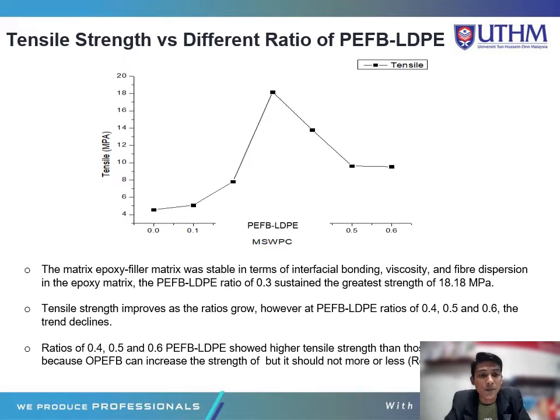The epoxy matrix of the filler matrix was stable in terms of interfacial bonding, viscosity, and fiber dispersion in the epoxy matrix. PEFB ratio 0.3 sustained the greatest strength of 18.18 MPa. The tensile strength improved as the ratio grew. However, at PEFB ratios 0.4, 0.5, and 0.6, the trend showed declines.